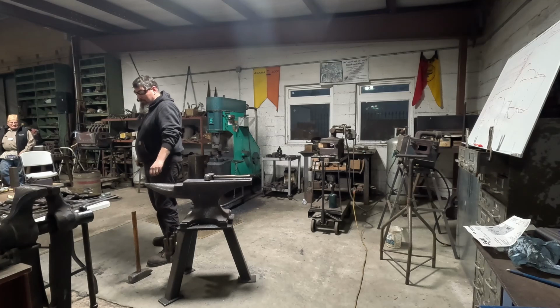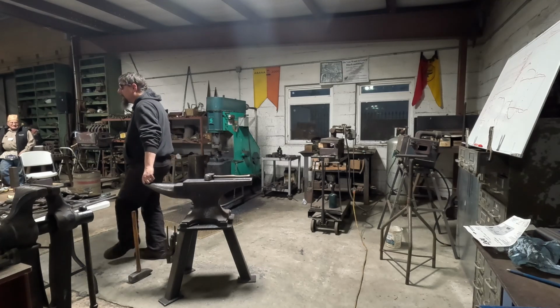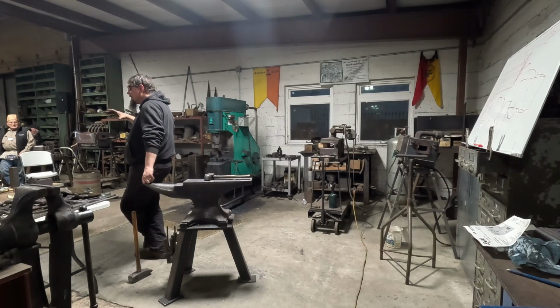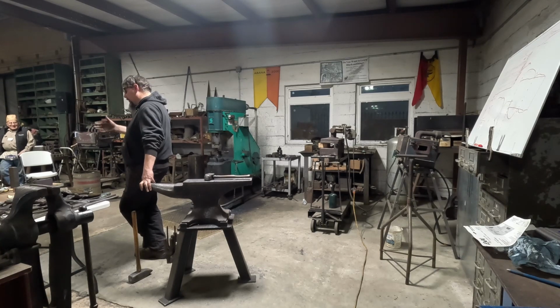And I tried to figure out how it happened, because it happened on the inside of a big ring. We started by taking a solid piece and punching a hole in it and then putting a pin through it and opening it up on a mandrel, which I had described a little bit last night. And the problem was primarily in the ID of the ring. It was tearing up, and the guys were having all kinds of trouble, so they called me and we looked at it. It was sort of beyond salvage by that point, so we let it cool off.